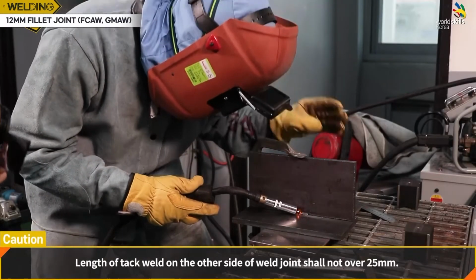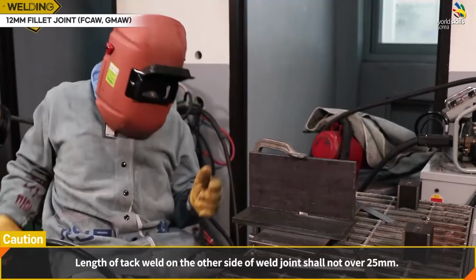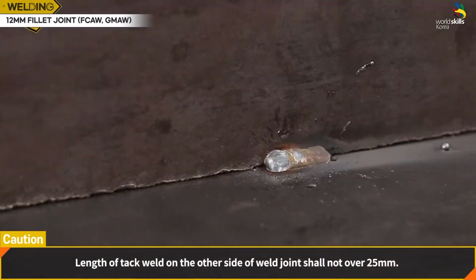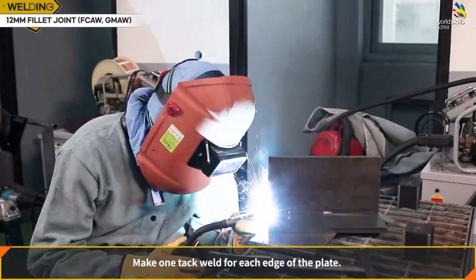Remove the magnetic base and make 1 tack weld on the opposite side of the weld joint. The length of the tack weld on the other side of the weld joint shall not be over 25 millimeters. Make 1 tack weld for each edge of the plate.